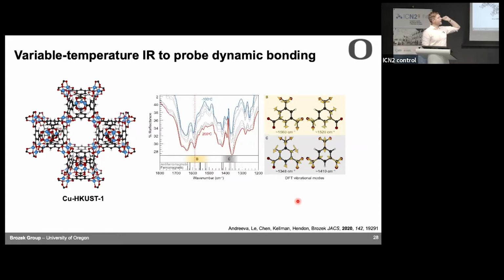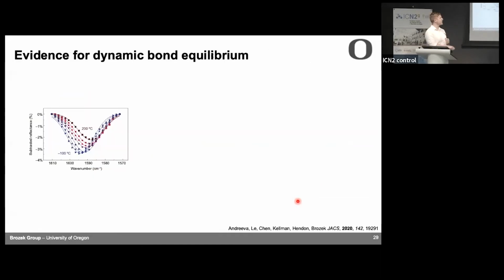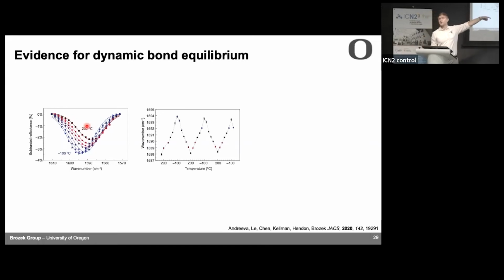And it turns out that every band that was redshifting had some carboxylate character. If a band had no carboxylate character, it didn't redshift. So that's telling us something interesting about MOFs, is that the carboxylate is really localizing all of the structural changes that happen when you heat up a MOF. Everything else seems to be mostly fixed. So that was interesting for us. So we can focus on the asymmetric stretch. When we normalize the data, we see that it obviously is redshifting. It's reversible. So we were worried that we were just destroying the MOF, but it's reversible. You can cool it and it blue shifts. You heat it again and it redshifts.